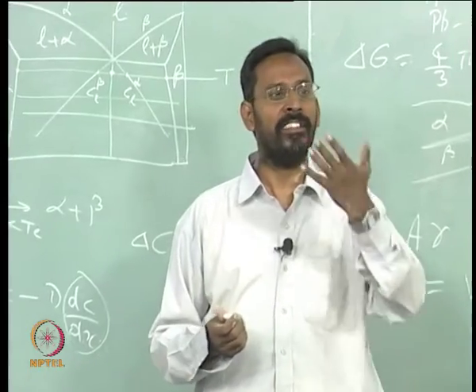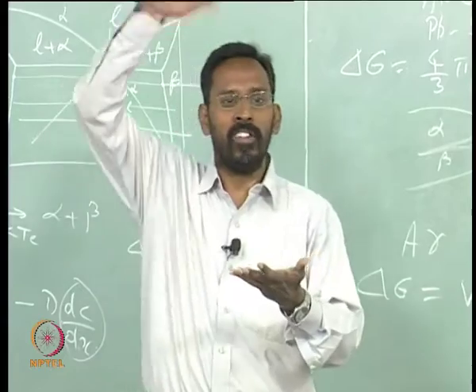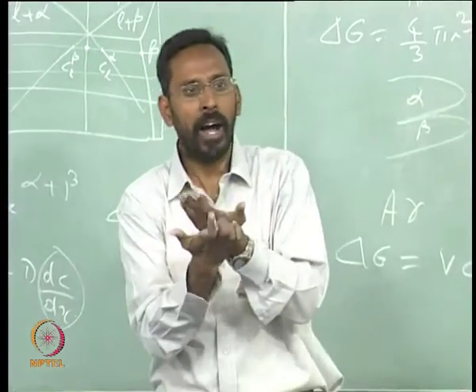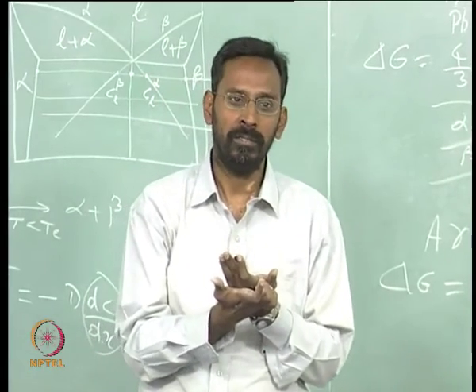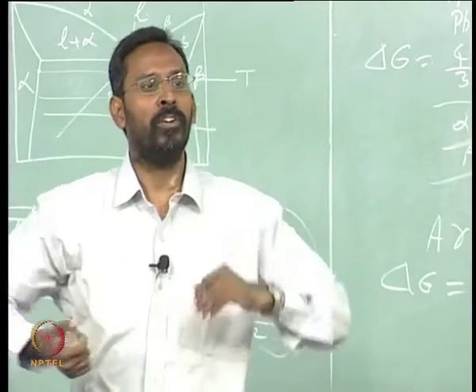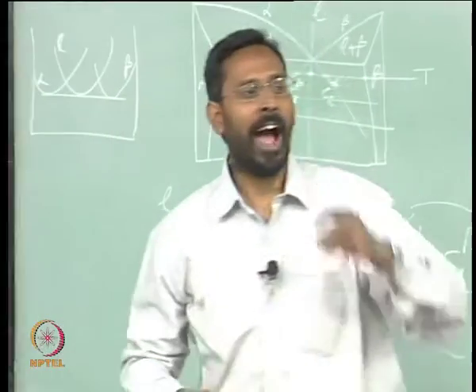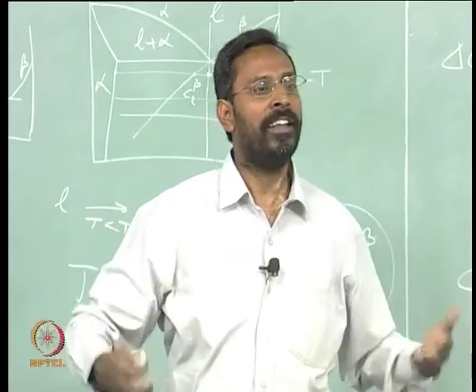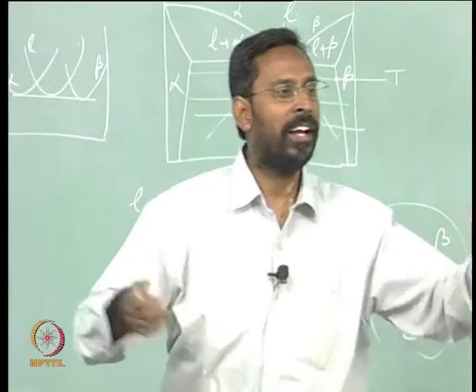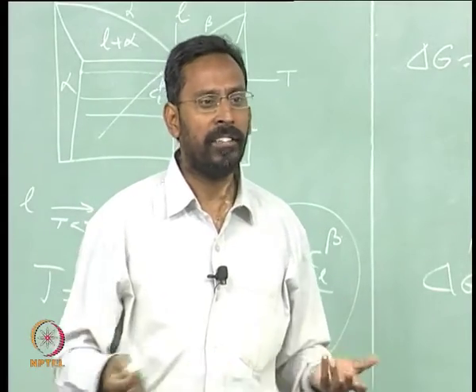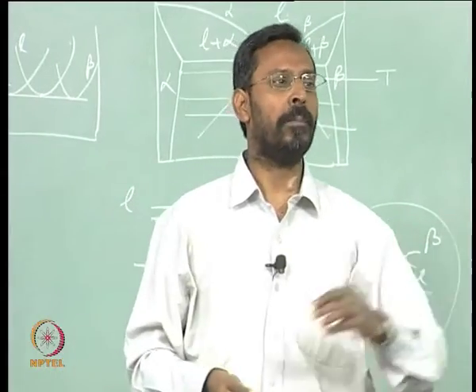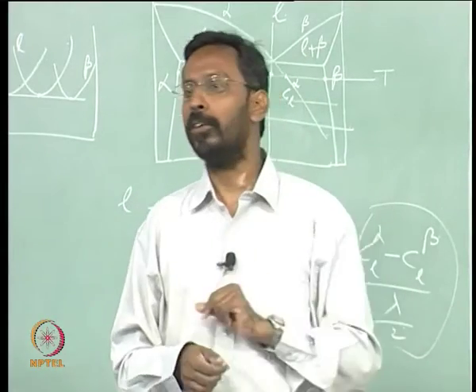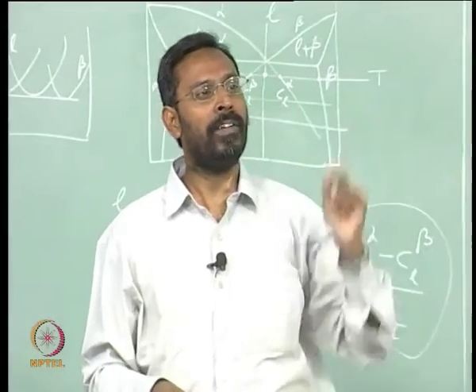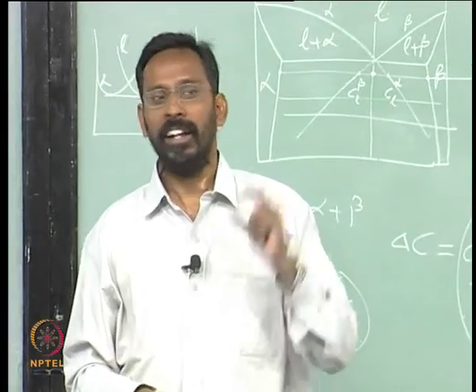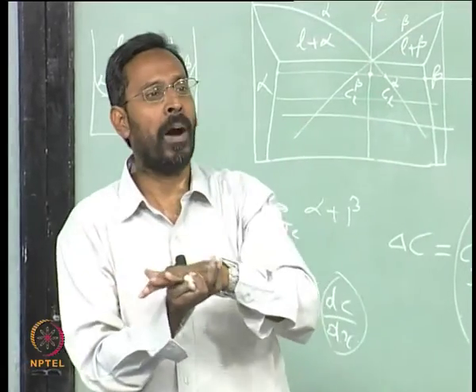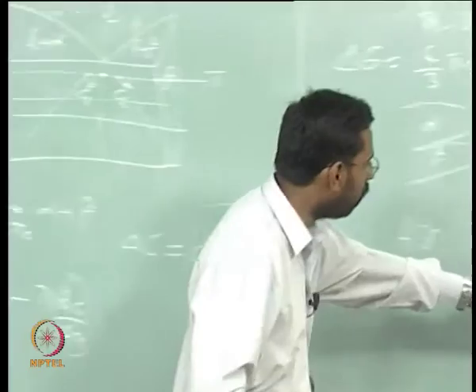A heterogeneous nucleation site is a site where the interfacial energy between the solid that is nucleating and the particle that is available is very small, and that is the reason why you see heterogeneous nucleation occurring. If you just add any type of particle to a liquid, it does not give you heterogeneous nucleation. Simply take aluminum, add some sand particles to it - it does not give you nucleation, though you may say sir, there are particles available. That particle you are adding should have structural compatibility with the solid that is nucleating, such that the interfacial energy between the solid and the particle is very small, so that this is minimized.